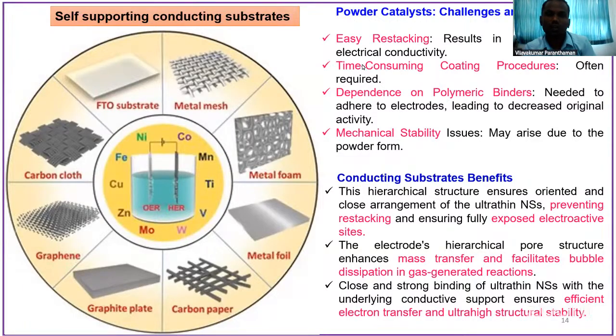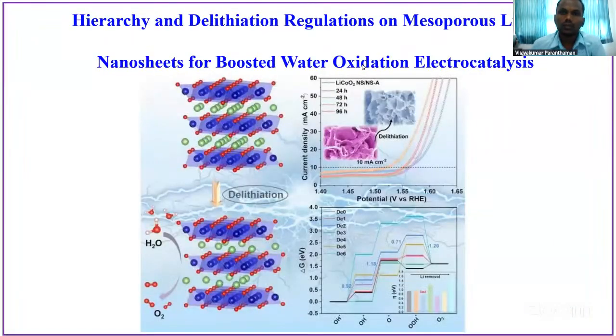There is strong binding between your material and the electrode, as well as high mechanical stability. So electron transfer, compared to the powder, is very fast over the substrate material, and so is mass transfer. The bubble detachment is higher than with the powder material. So we have decided to use one of the substrates for our experiments. Then, based upon our literature reviews and deep research, we have decided to synthesize some two-dimensional materials combined with one-dimensional material, and again two-dimensional material combined with two-dimensional material.